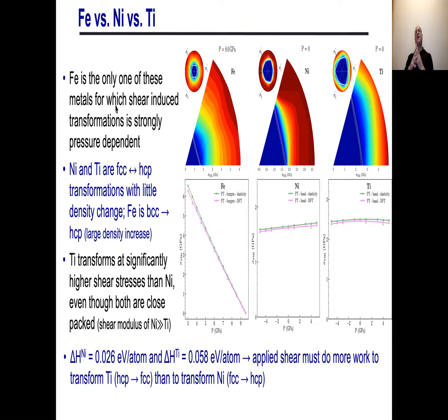Okay, so if I look at the iron, nickel, and titanium data together, what do I see? First, iron is the only one of these 3 systems for which the phase transition is pressure sensitive. Nickel and titanium are very pressure insensitive. And again, that's because the phase transition between BCC and HCP iron has a big volume change, therefore a large pressure difference. That's the P delta V term.